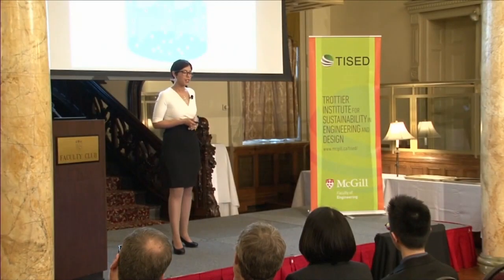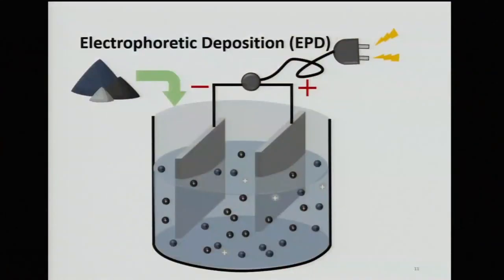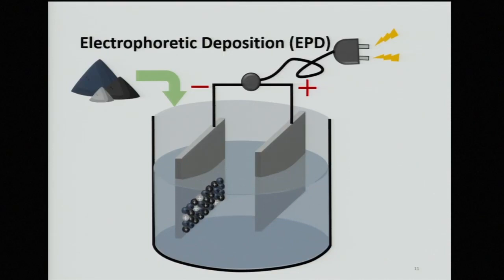If we then take the metal surfaces and connect them to a power source, it forces a charge to also develop on these surfaces. As a consequence, the powders will migrate towards the oppositely charged surface and deposit. This gives us the painted layer that we then use as an electrode.